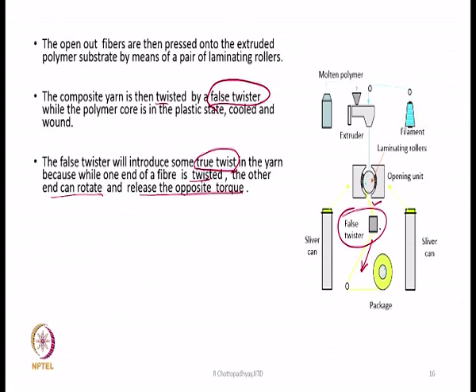When the other end cannot release the torque, that means in that case the torque present in the front part of the fiber and the back part of the fiber. This back part and front part is in reference to the false twisting unit's position. So, when the part in front of the false twister and the part behind the false twister both have exactly the same amount of torque, in that case whenever the part behind the false twister moves downstream, they lose all the twist, because the torque will cancel each other, because they have different senses.